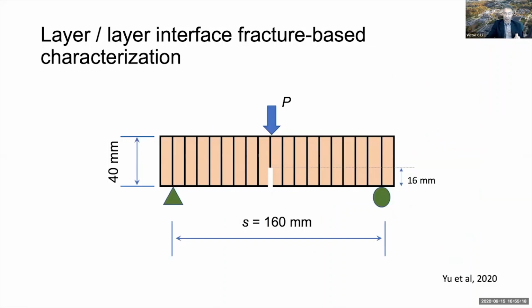Because of the higher porosity in the material near the interface between two layers, one can also expect that the interface would be weaker. And not only that, but also because of the potential lack of fiber bridging across the interfaces. In consideration of this effect, we conducted a study of the interfacial fracture behavior by casting a wall of layered ECC and then cutting it and turning this 90 degrees, and then introducing a notch and subjecting the whole assembly to a 3-point bending test.